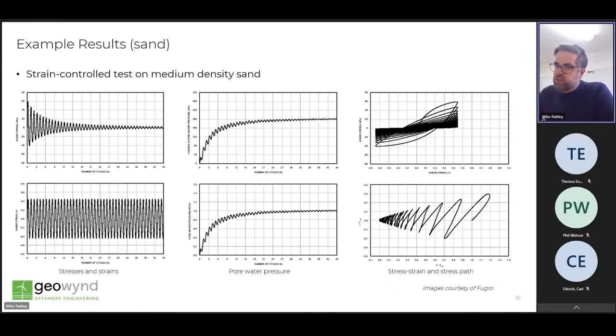This slide presents a strain control test on a medium density sand, so density not dissimilar to the previous case. But in this case, we see that the shear stress here is degrading because we're applying a constant amplitude shear strain instead of a constant amplitude shear stress. So what we have is a degradation that occurs with number of cycles and an accumulation of excess pore water pressure, which occurs reasonably rapidly until the effective stress approaches the zero point over here, and then a residual stress state is achieved at a higher number of cycles. And indeed, this is an example of the type of test that Carl referenced with regard to looking at residual stresses in soils.